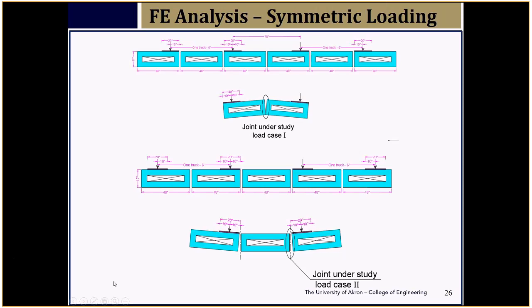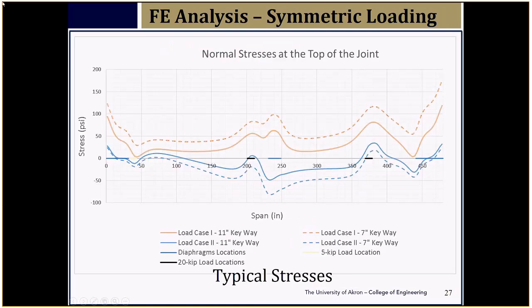So progressive development of cracks is a bad thing because we are assuming that we have 6 plus 3, let's say 7 inches of joint depth initially to start with, but as the cracks progress, our joint depth is reducing from 7 inches to maybe 3 inches or 4 inches or whatever that is. So we looked at these load conditions, and what we found was deeper keyways